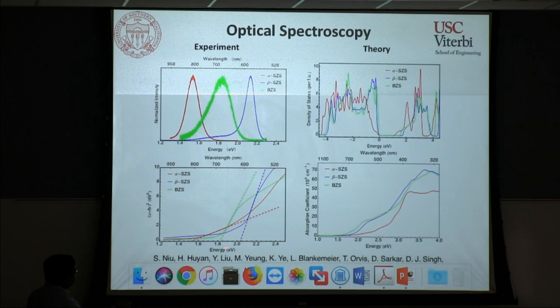And if you look at the diffuse reflectance spectra for the powders that we did, these values match closely with this. There is an offset because typical DFT calculations always underestimate band gap, but overall the trend was very similar to what we would expect. Not only that, when we did photoluminescence measurements, we were able to identify macrocrystalline particles in those samples that gave intense luminescence that allowed us to confirm that the diffuse reflectance studies showed the right band gap values.